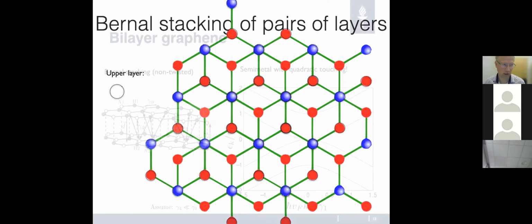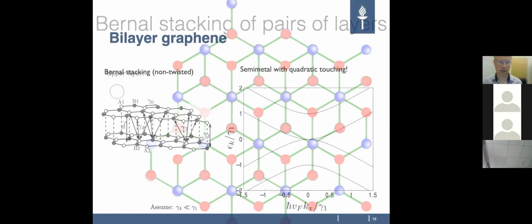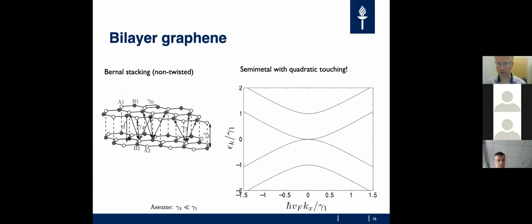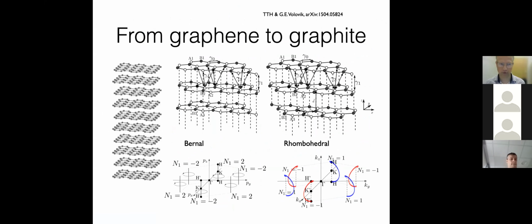If you just have a single pair, you have bilayer graphene. As is quite well known in this case, from the Dirac spectrum you go to a semi-metal with quadratic touching, at least in a certain approximative model. Now, if you want to continue the stacking, you go, of course, to graphite, and there are two extreme versions of graphite stacking. There is the so-called Bernal graphite, which is the most stable configuration, and then there is a metastable rhombohedral configuration, where every pair of layers always has the same Bernal stacking that I showed before, but which atoms are on top of each other changes. And actually, both of these graphites are very interesting nodal line semi-metals.